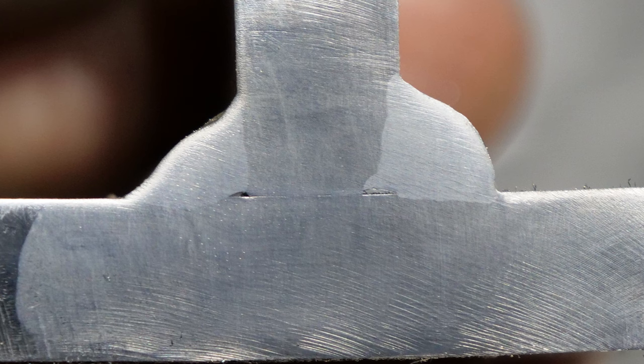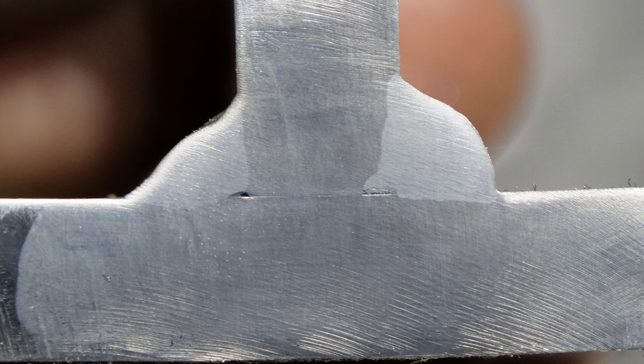Which is really bad when you look at it - there's no root fusion at all, pretty weak weld, but not ideal. The other thing you can notice is the sheer amount of weld metal that was put down for that flux core weld. You can see how much bigger it is in that single pass. With MIG I was just trying to deposit too much metal, moving too slow and welding on top of weld rather than letting the wire eat away at the root.